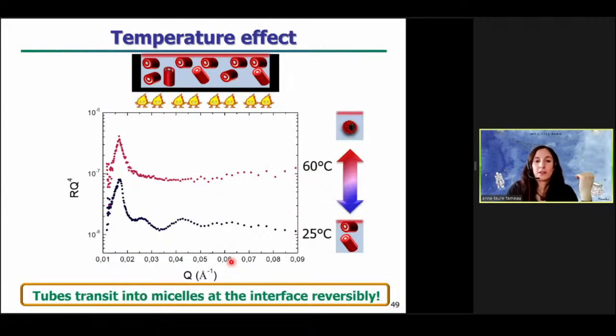Then we wanted to study what is happening with the temperature, because I showed you previously that tubes turn into micelles with the temperature, and we wanted to determine what is happening at the interface. So we just recorded the reflectivity curve at 60 degrees, as you can see here in red. And we don't see anymore the presence of interference fringes, and we can easily fit this curve with just a fatty acid monolayer at the interface.